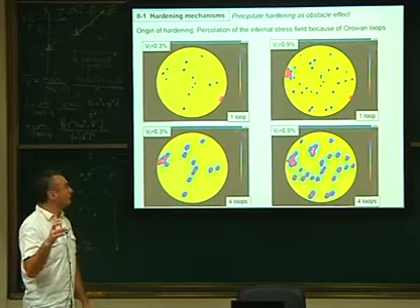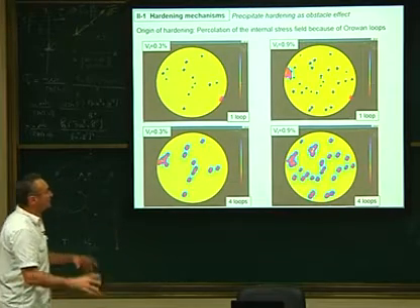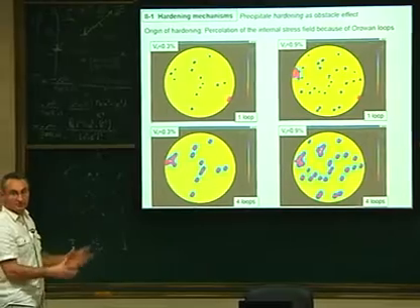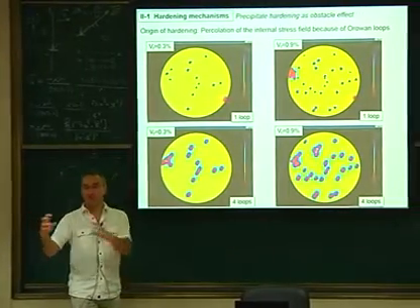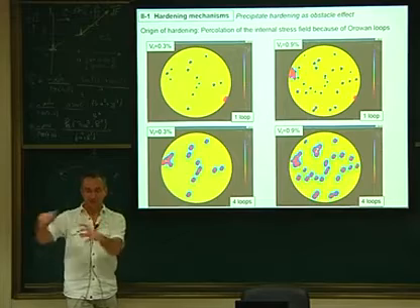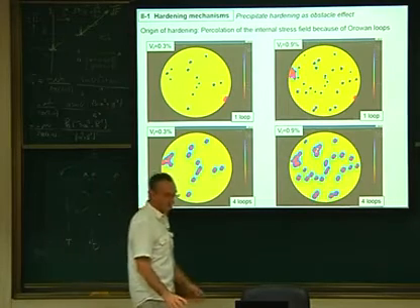There is what I will call the Orowan internal stress. This is a kinematic hardening, actually, which is a collective effect, just because they interact together. And what you thought was a single particle could now be a bigger one, just because it has merged with the neighbor particle, because of the Orowan looping.